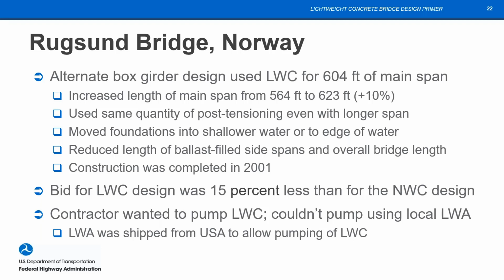And it turns out that once again, in this case, the contractor wanted to pump lightweight concrete, and the Norwegian DOT wouldn't allow pumping of the local lightweight aggregate. So here, the lightweight aggregate was shipped in from the United States to this project, and the bid was still 15% less than the normal weight design. And that's because of the changes to the design that were possible because of the lightweight concrete.